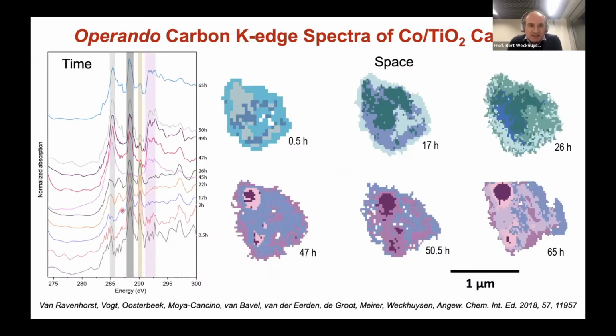But the carbon spectra are even more interesting. And what I mean by it is that you see here 0.5 up to 65 hours. It's about, let's say, 3 days. This is far from trivial to do, 3 days of an experiment where you follow the same particle as function of time in a reactor under pressure and high temperature. Nevertheless, we succeeded. And here I show you the space resolved maps and the time resolved maps.